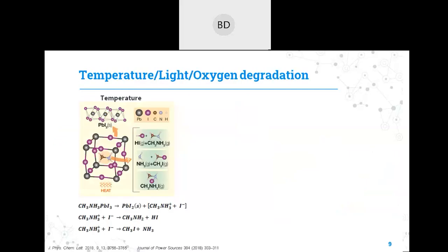If you talk about the factors affecting the degradation of the perovskite, the perovskite material is very sensitive towards temperature also. The structure of the perovskite contains methylammonium, which is the organic part and has a volatile nature, and even the halide has a volatile nature. So if you give heat of more than 85 or 90 degrees for a longer time, it starts disintegrating because of the volatile character of iodine as well as the methylammonium.